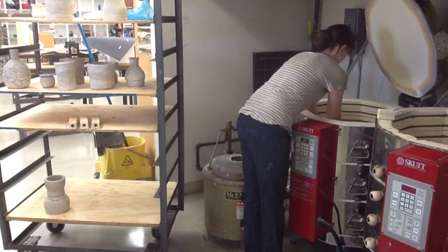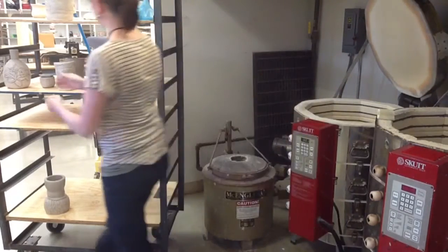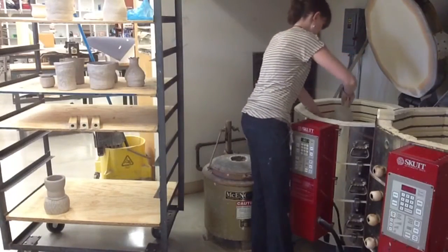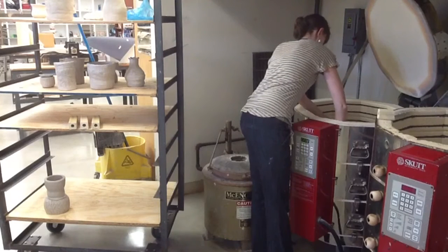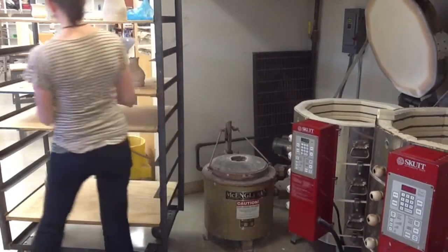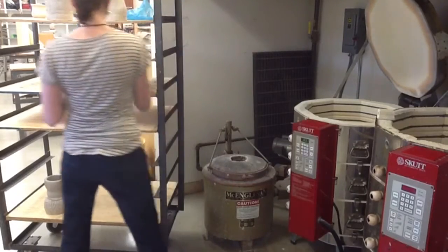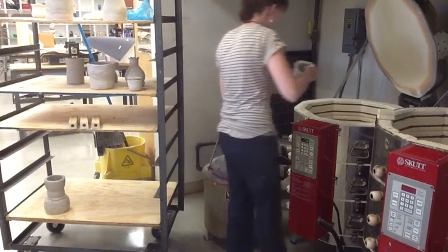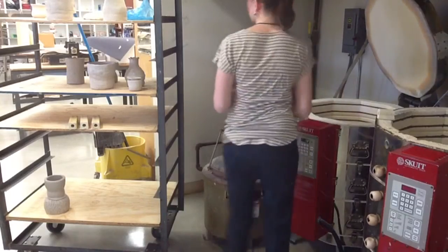You'll notice that I don't necessarily pick up and put every piece into the kiln. If it feels really thick and still very cold, it's okay if it's a little cool because I'm going to ramp this up at a slow speed versus a medium or high speed, so that way if there is any little bit of water left it will evaporate slowly and doesn't blow up in the kiln. However, if it feels too cold I don't want to chance it either — with blowing up that piece or even the pieces next to it. That's why having that pinky width is very important.